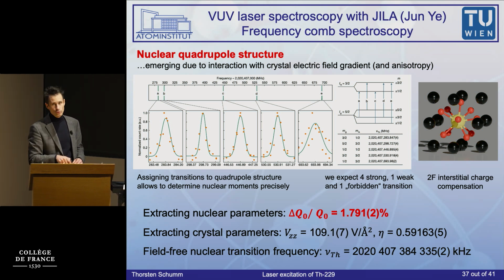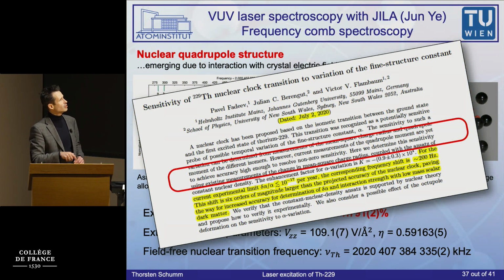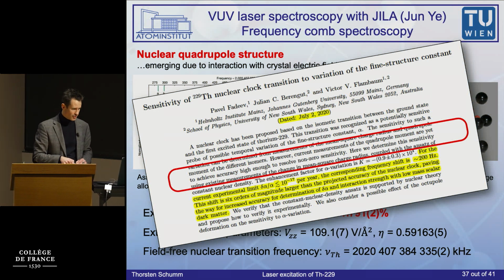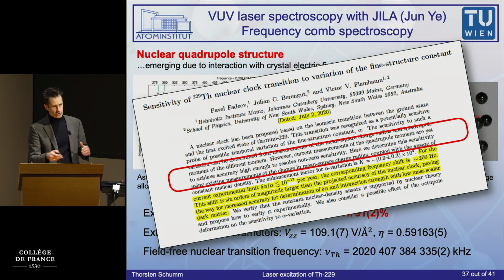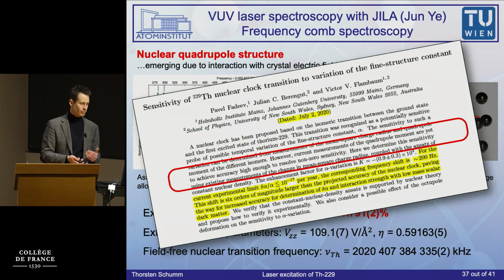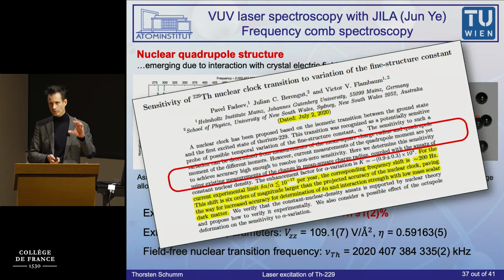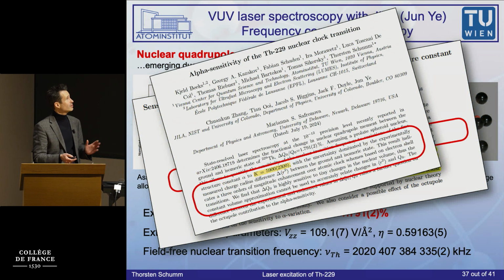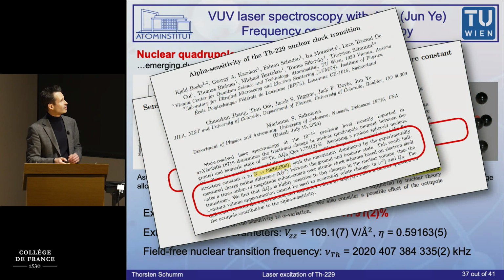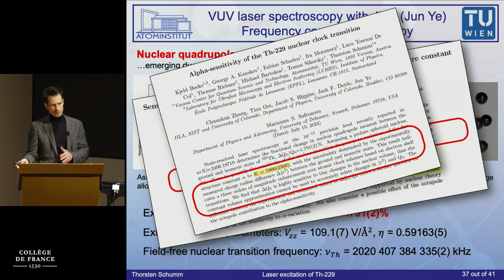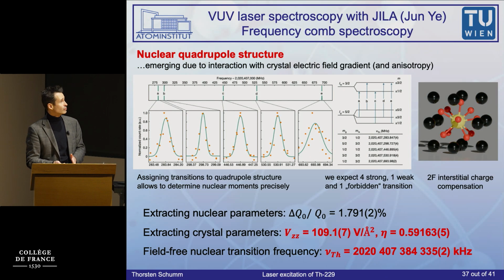So this is looking at nuclear parameters, and this is exactly the nuclear parameter that was missing in the theoretical models for Victor Flambaum in order to determine this enhancement sensitivity parameter that determines how easy or hard it will be to measure variations of fundamental constants by looking at this energy very precisely. So we've been able to do that in collaboration with Jun, Mariana Safronova, and my team, and it turns out that the factor is about 6,000, which is the same order of magnitude as what Victor predicted, but has a different sign, actually. So that's nice. We can actually do reasonably interesting nuclear physics experiments doing laser spectroscopy.